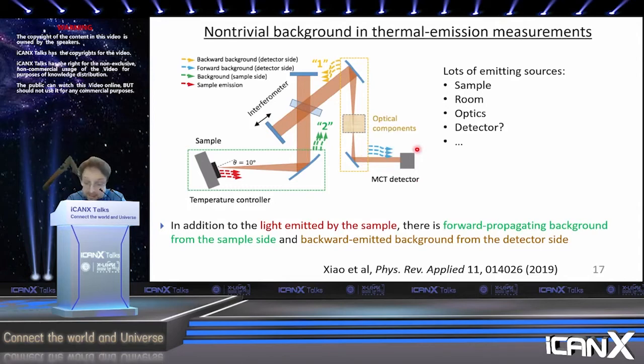But as I discussed a little bit earlier, we also have a very large thermal emission background. That means that not only is the sample emitting, but also, for example, various optics and apertures in our complicated setup are thermally emitting. And it turns out that the backward emitted background, so if you have some optical components over here emitting light in the backward direction, and some of that light hits the interferometer and comes back to the detector, that's what contributes to this very strange situation where the detected light goes down and then up again as the temperature is decreased. I want to show you a little bit about how that works.